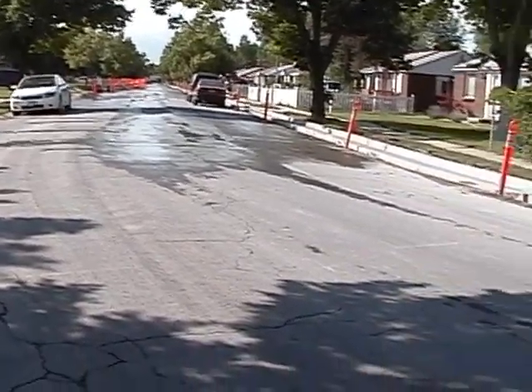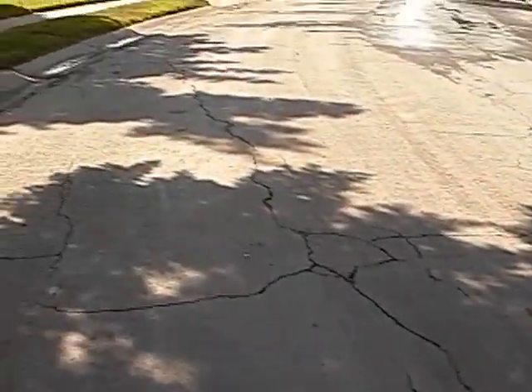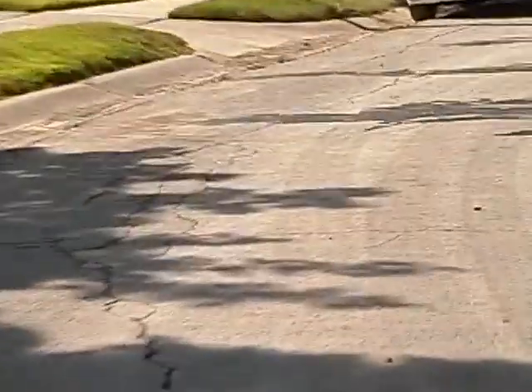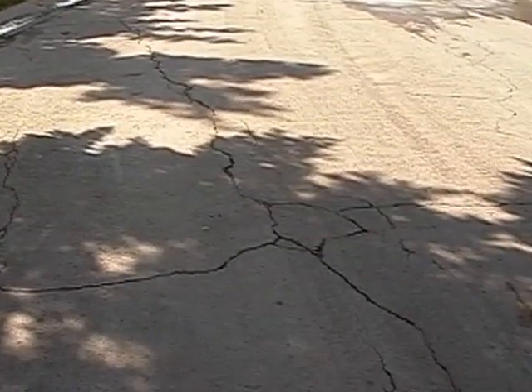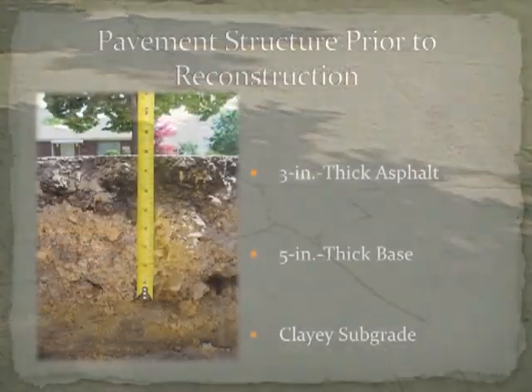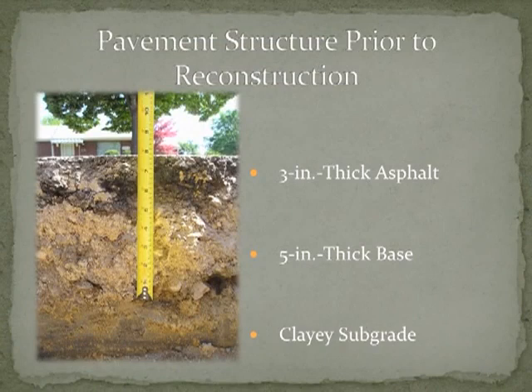Redwood Drive, prior to reconstruction, suffered from severe pavement failure due to fatigue cracking and insufficient drainage that resulted in ponding. The average International Roughness Index reading prior to reconstruction was 155 inches per mile, which is characterized as fair according to the Federal Highway Administration. The pavement structure consisted of 3 inches of asphalt, 5 inches of road base, and a clay subgrade. California bearing ratio values for the subgrade were generally between 5 and 10.